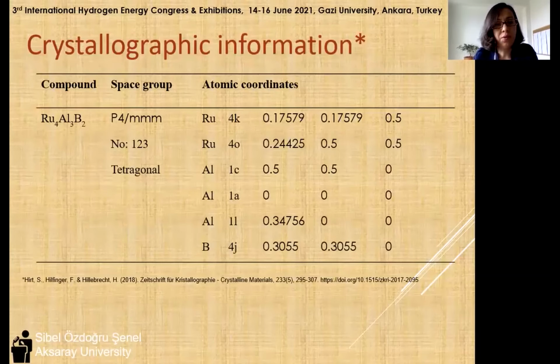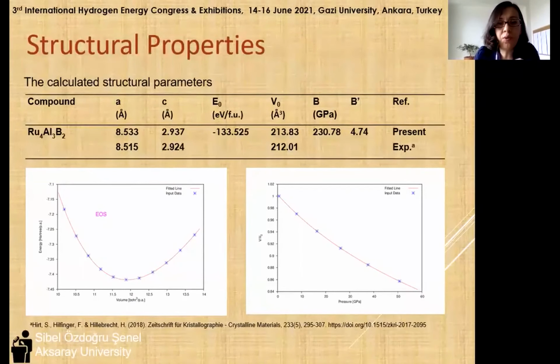Here, basic crystallographic information is given for ruthenium, aluminum, boron, which is also the first input data for the calculations. The compound has tetragonal geometry. This information was taken from the experimental study given below. The Ru4Al3B2 compound crystallizes in a tetragonal structure and contains 18 atoms in the unit cell. Structural parameters and literature values calculated for this compound are given in the table. The calculated structural parameters agree reasonably well with experimental values.